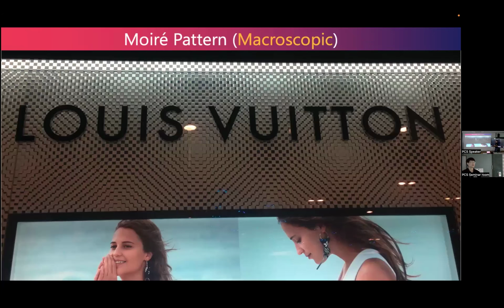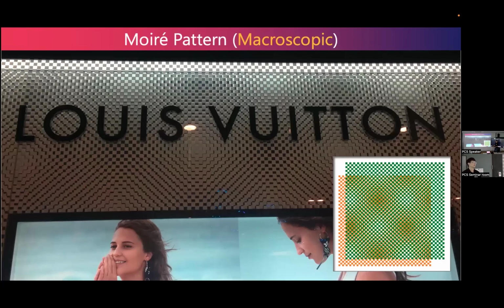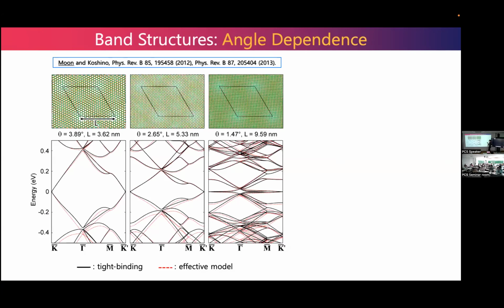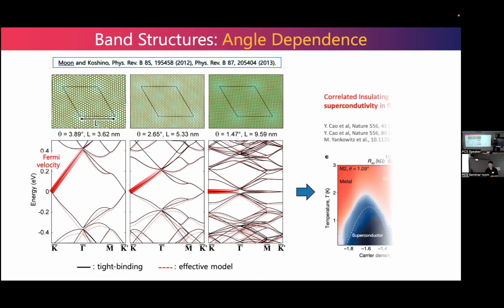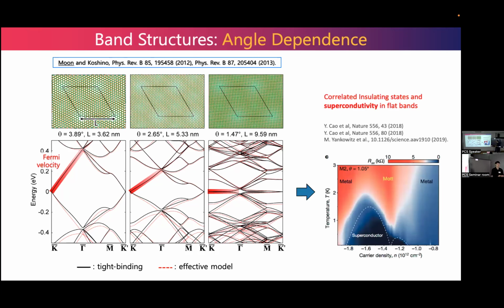Moiré patterns are quite common in real life, and a similar thing happens in microstructure as well. For example, by stacking two layers of graphene and twisting them by an arbitrary angle, say 1 degree, we can change the Fermi velocity and even the characteristic energy scale. And yeah, we can even make superconductivity in this system.